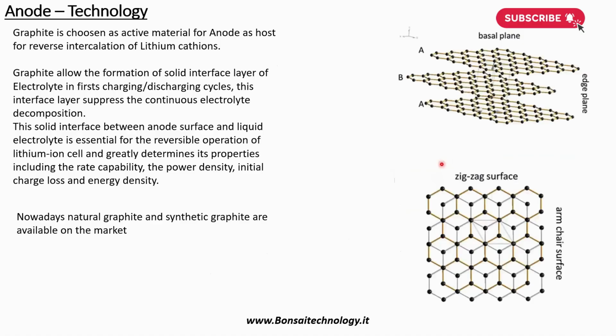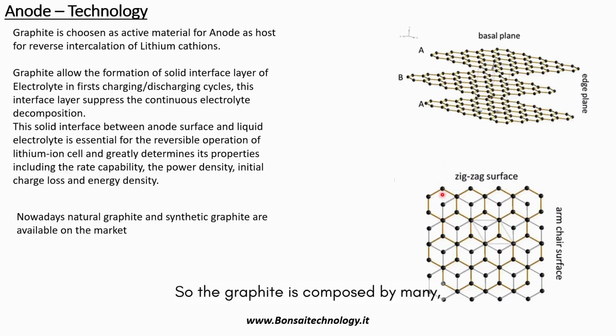So how does the anode work? In the beginning it seems difficult to understand, but it is really, really easy. I mean, as you know, the graphite structure is defined by basal planes. So the graphite has a hexagonal reticulum arranged in a plane. Okay, so the graphite is composed by a stack of planes, where the atoms lay on each plane. So during the charging and discharging of the batteries, the lithium ions move between the basal planes. Okay, so the lithium ions are moving from plane A to plane B. And this increases the volume of the active material in the anode.